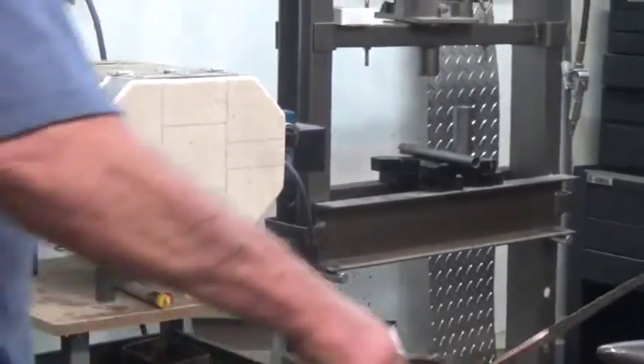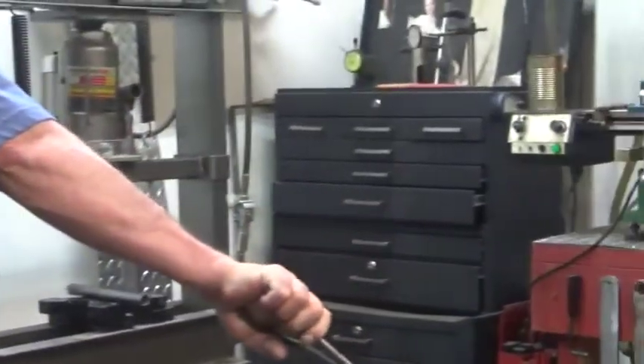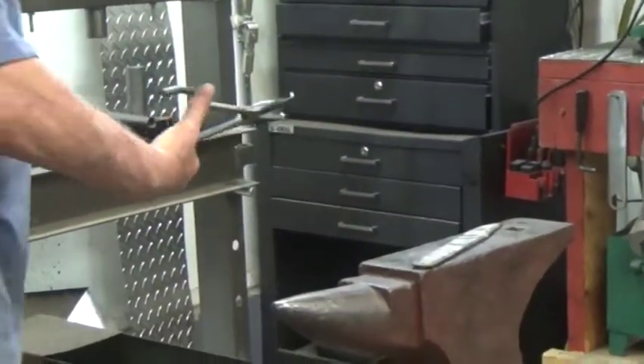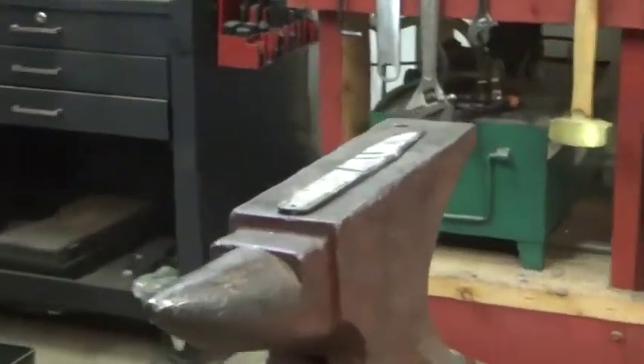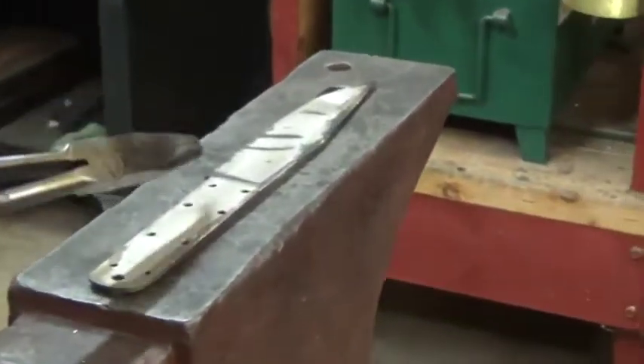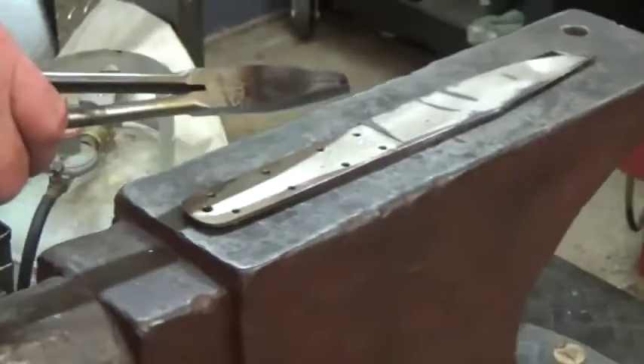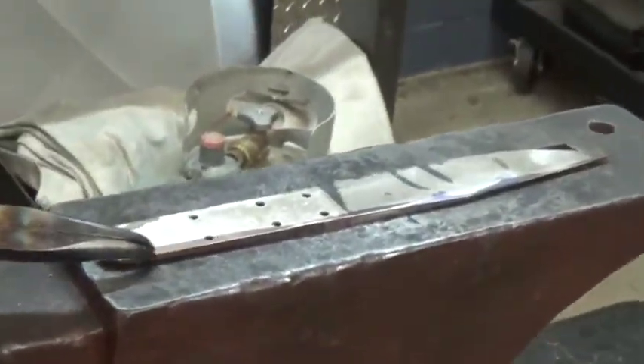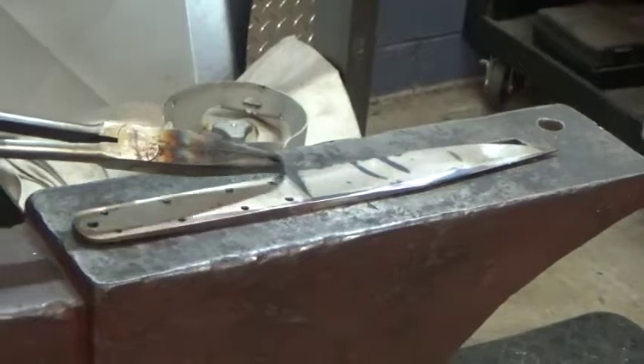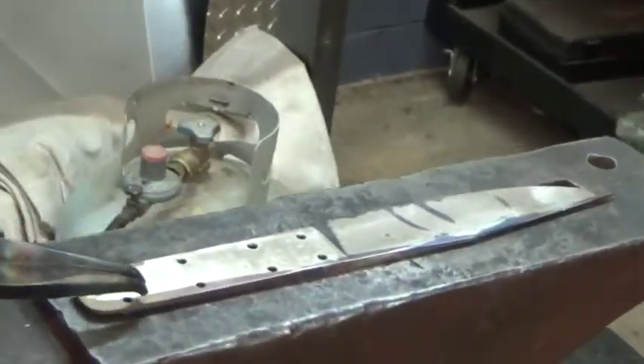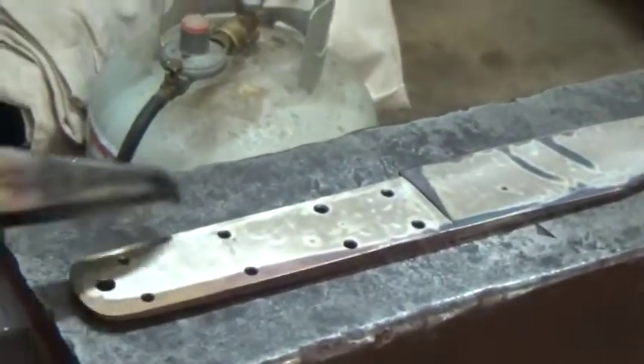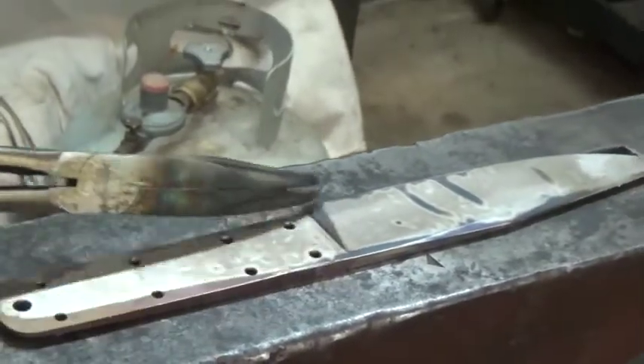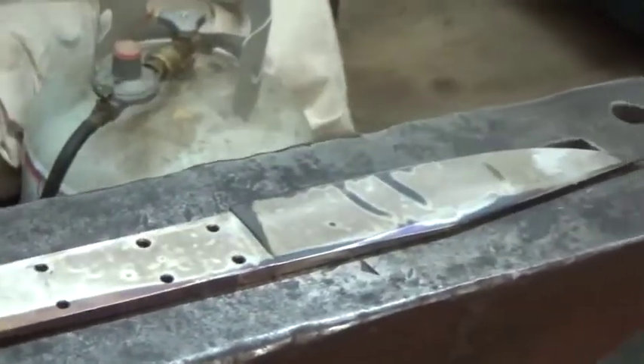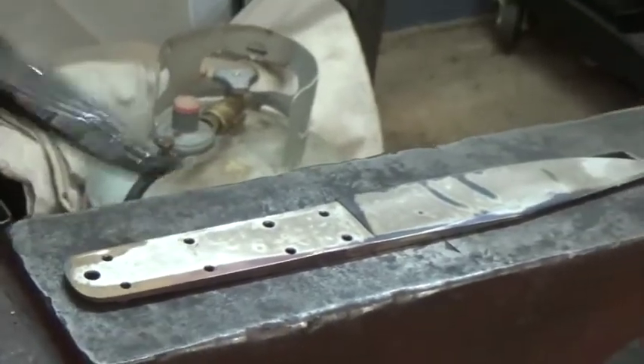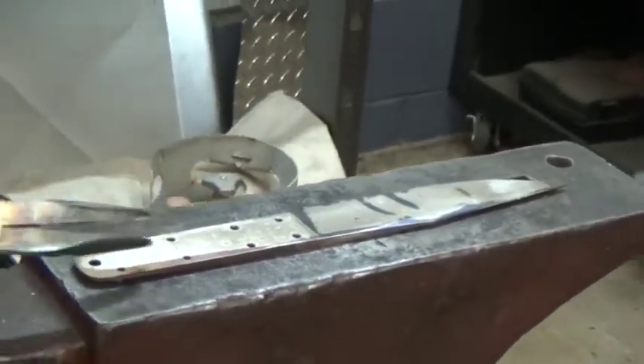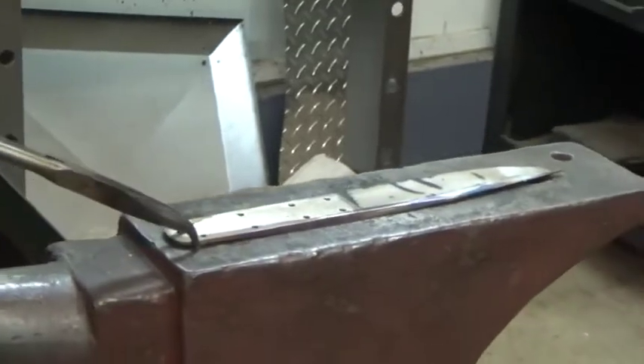Okay, it's out of the drawing furnace. So that's going to finish out to about a Rockwell 60, 58 to 60. One of the byproducts of foil wrapping is you get these color streaks, but the ones you can see show you the color that you're wanting, that purplish blue. But it's tempered or drawn through and through. So it's letting this anvil suck the heat out of this thing.